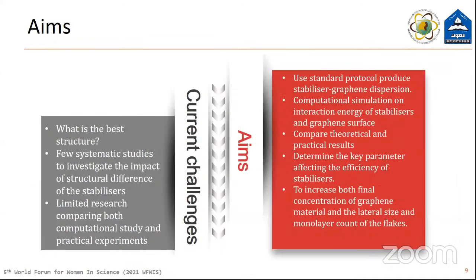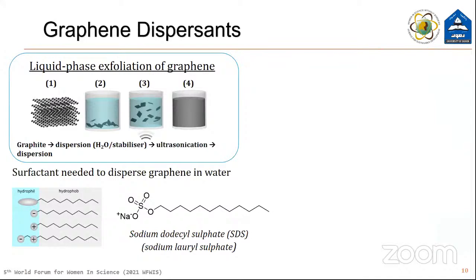For this reason, the aim of my study was to use a standard protocol to produce stabilizers for the graphene dispersion, and then we conducted some computational simulation on the interaction energy of a stabilizer and the graphene surface. Then we wanted to compare the theoretical and practical results and determine the key parameter affecting the efficiency of stabilizers, to increase both the final concentration of graphene material and the lateral size and monolayer count of the flakes.